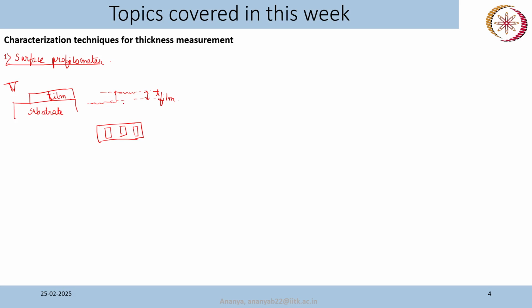So for accurate thickness measurement, we go for photolithography to make this kind of profile, with multiple steps, so that you can measure your thickness reliably. One more advantage of making multiple steps is that there may be some difference in thickness from one corner to the other. If you are not careful with your deposition techniques, you will get to know about the thickness variation along the x direction or y direction in your sample. Now, this is about the surface profilometer. The problem is that we have to go for photolithography to make this kind of step, so it is not a uniform film now. It is a destructive technique.